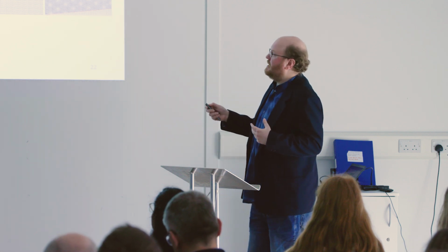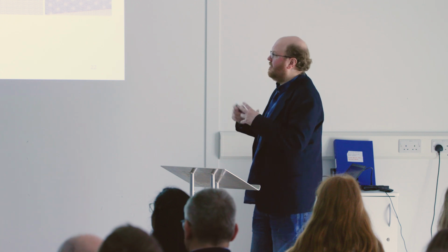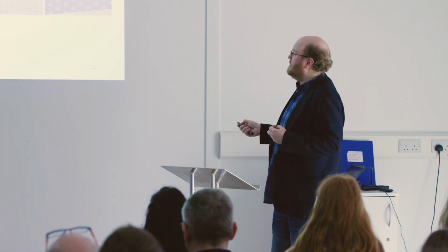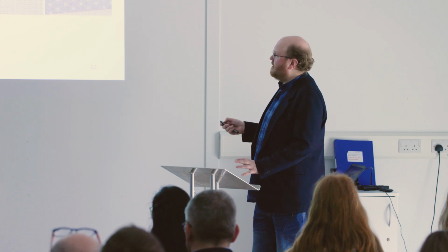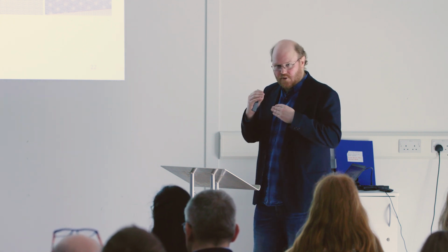And then we pyrolyze it at about 2,000 degrees, and that removes these defects. That completely gets rid of these carbon vacancies or any other remaining oxygen groups on there, etc. And you get back to a very nice, pristine carbon structure. You can see this moiré pattern that you get between the layers interacting with each other, showing that it's very defect-free. There's no atoms missing or dangling bonds or anything like that. So even though it's defect-free, we still have that absence of the stacking order that you would get in graphite. So the layers are still kind of independent of each other.